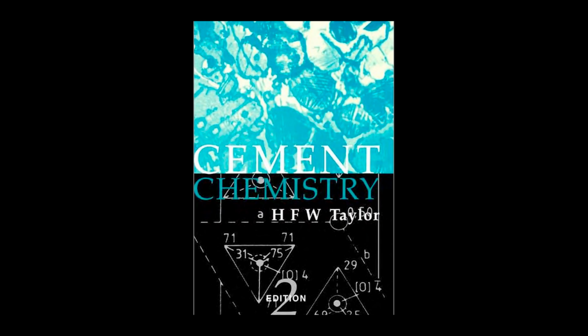Let's go back to MgO for a second. We need to keep it locked away. Does the quench help with that? Fast cooling is the chemical safeguard against destructive MgO. If you cool rapidly from high temperatures, say above 1500 Celsius, you force the MgO to remain in solid solution within the aluminate and ferrite phases, where it's benign.